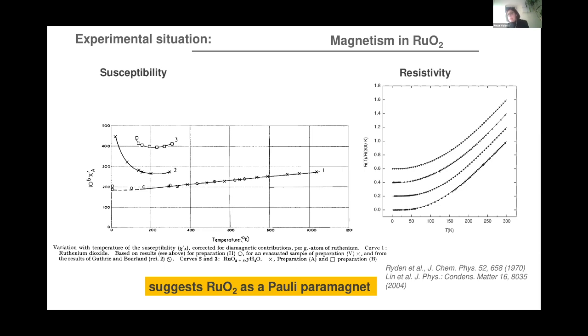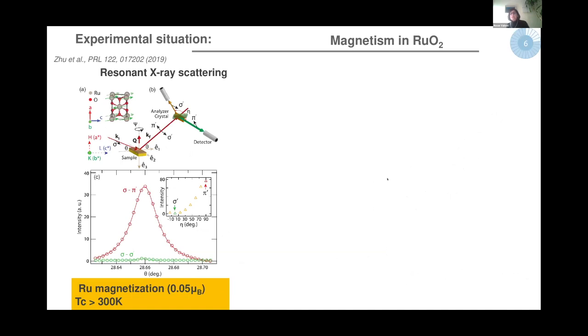The same if we look at the resistivity. The resistivity seems to show a very metallic behavior, so in fact typical of a Pauli paramagnet. So these thermodynamic measurements, transport measurements and susceptibility measurements seem to indicate that ruthenium dioxide doesn't order. However, there are also other, more recent experiments.